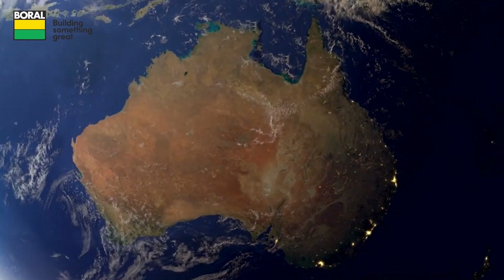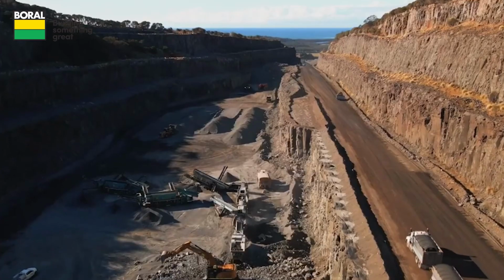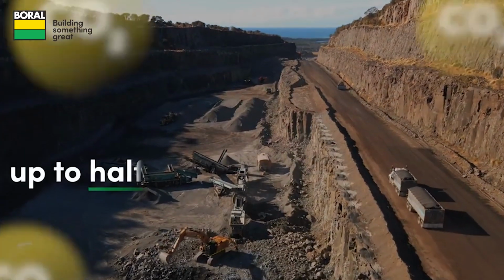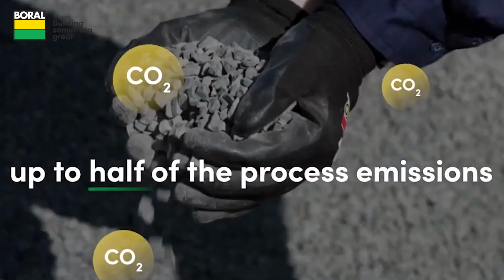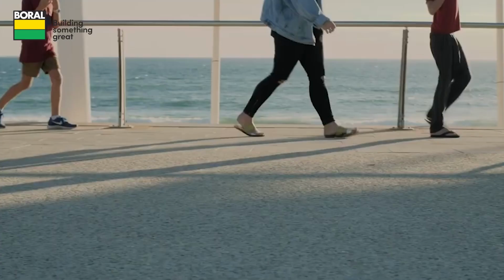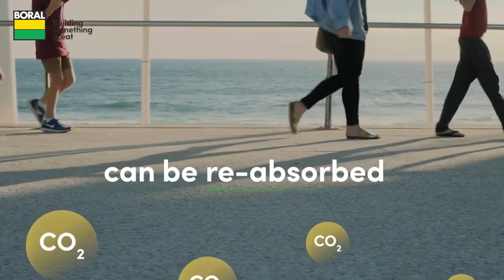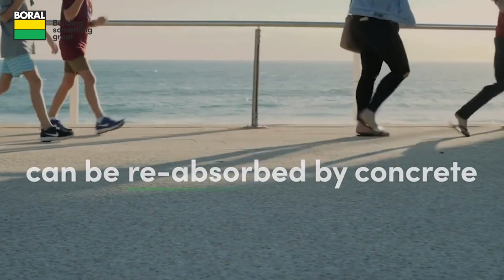To improve our technical capability in this space, we are in the commissioning stage of a carbon capture and utilization pilot plant based on recarbonation at our Berrima cement manufacturing site. Recarbonation is a well recognized process and is estimated that approximately between 20% to 50% of process emissions during manufacturing of cement can be reabsorbed by concrete throughout its service life.